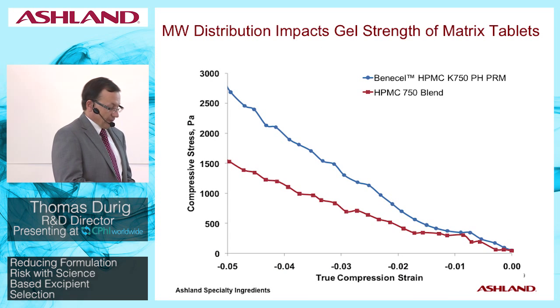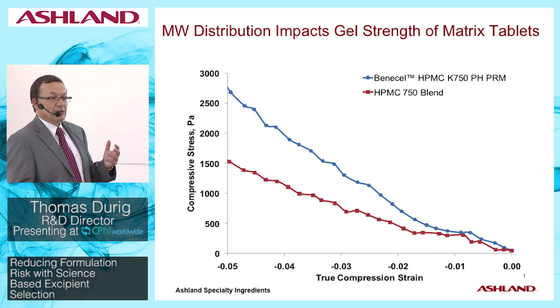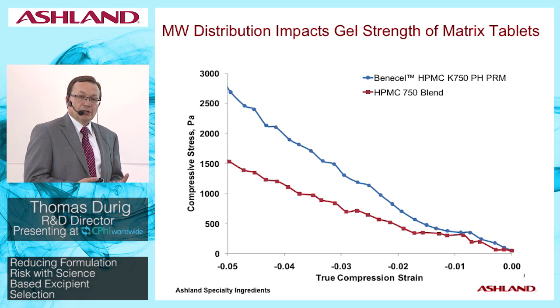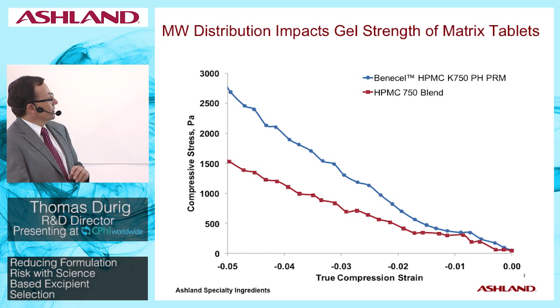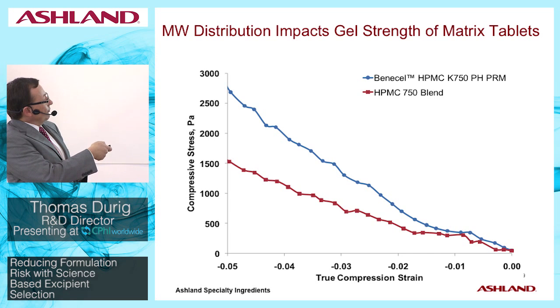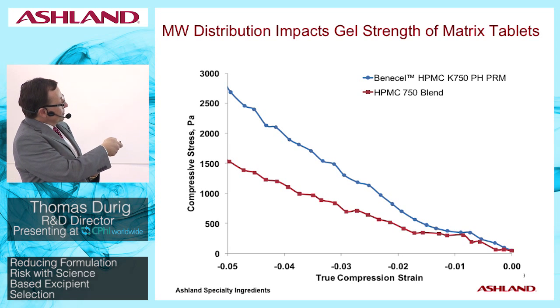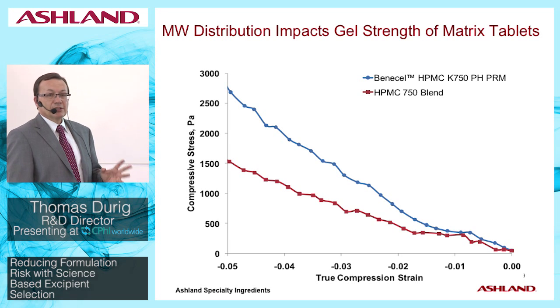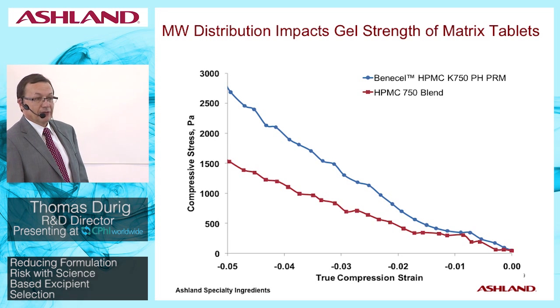And this is very, very significant because if we actually then look at the properties of this gel-forming tablet, here we have the gel strength for the HPMC tablet containing the blend, that's the red line, and then the one where we have the custom-made HPMC with 750 centipoise, we see a significant difference in gel strength of these two, which is due to the fact that we have a different physical situation.